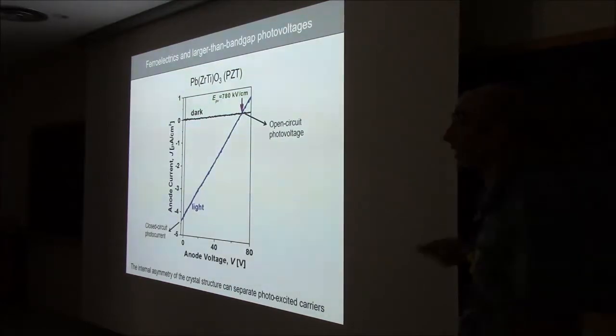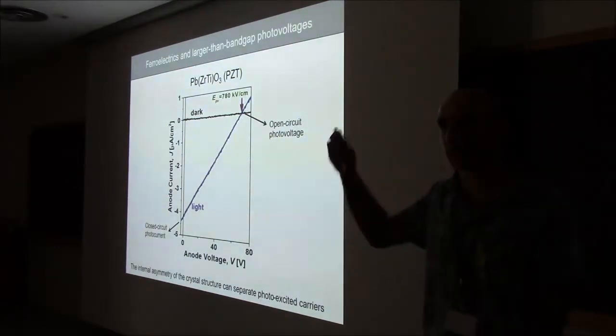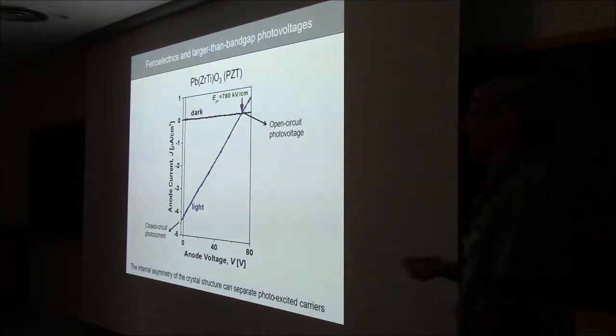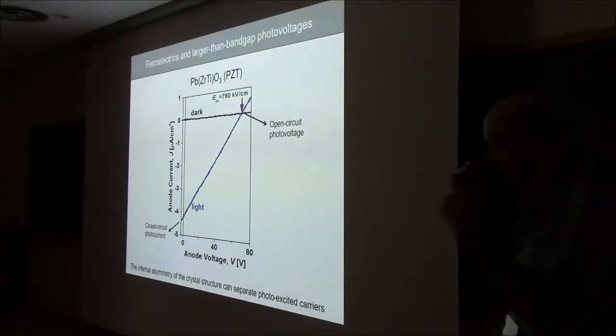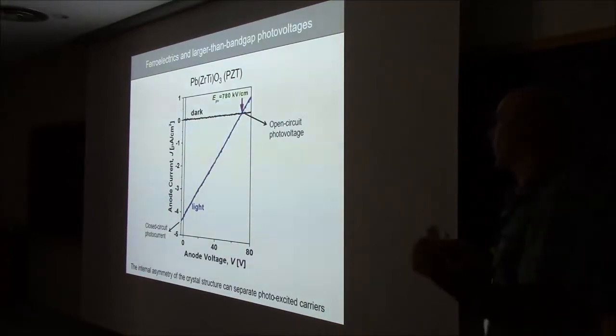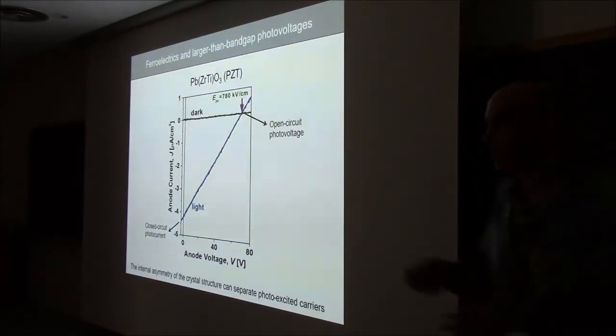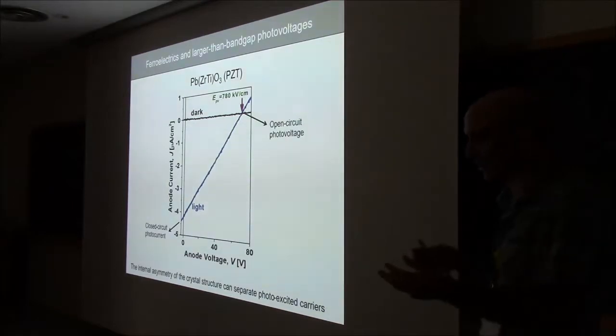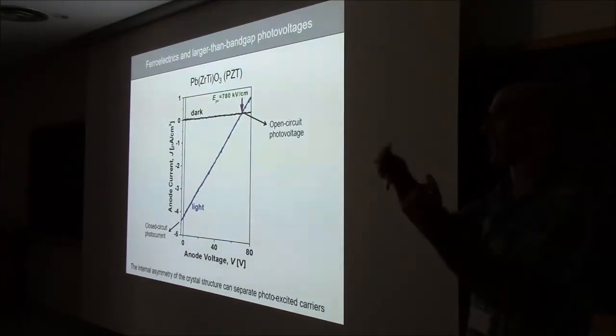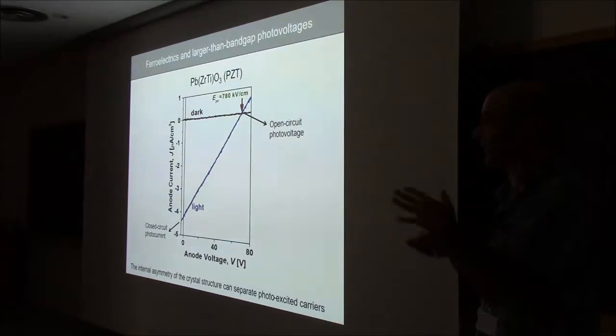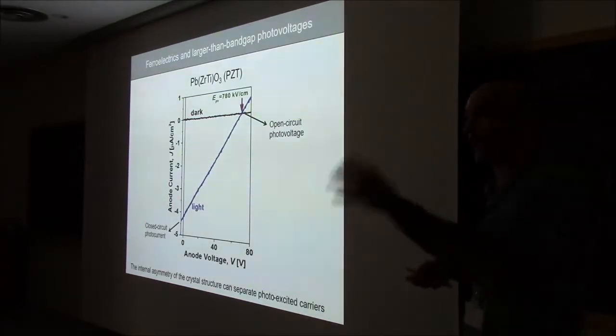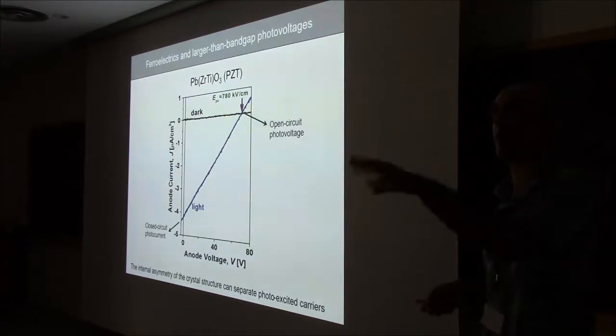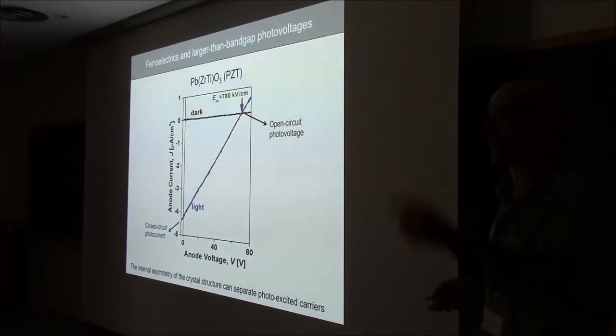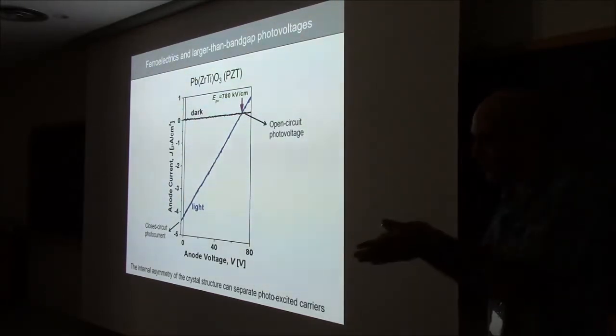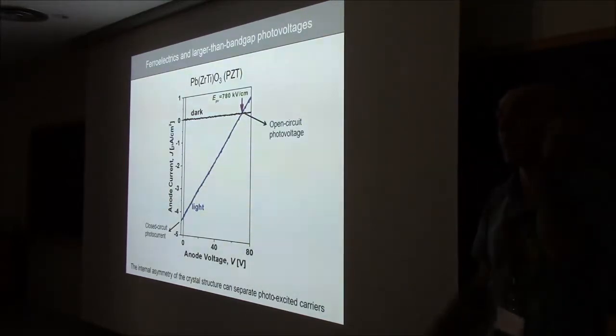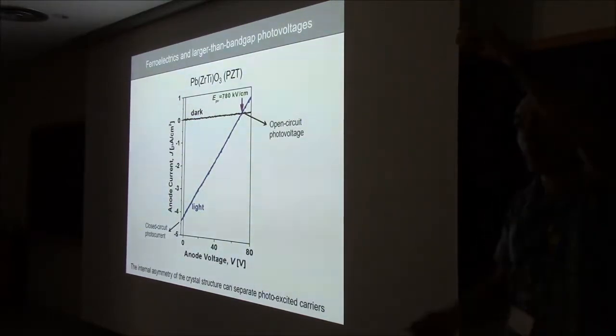Other interesting things about ferroelectrics, that's another futuristic application that does not exist yet, but people are hoping that it will exist, is to take advantage of the fact that the crystal lattice of ferroelectrics is asymmetric, which means that if you shine light into a ferroelectric, and it has to be light bigger than the bandgap, 3.5 volts, so you need to, in this case, it has to be UV light. If you want to do photoelectric experiments with the normal ferroelectrics, you need to use UV light.